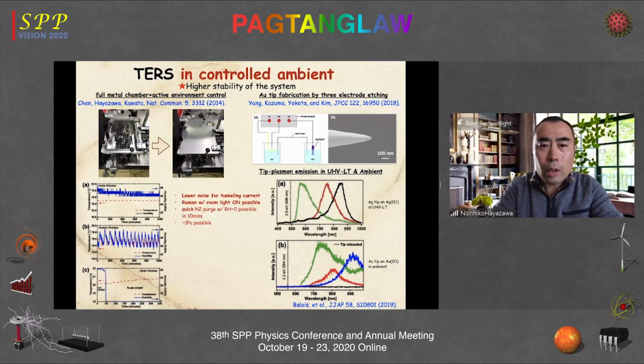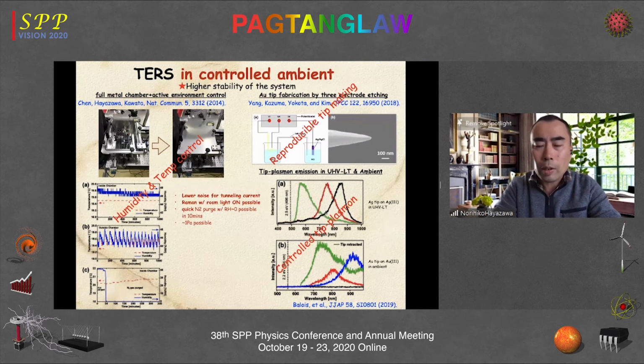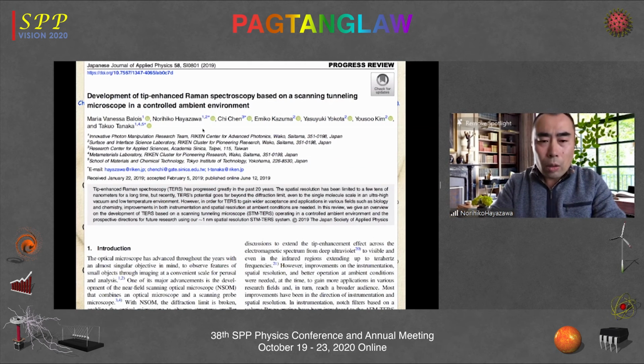After that, we have developed lots of optimizations in ambient tip-enhanced Raman spectroscopy. For example, the improvement of the humidity and temperature control using the environmental control chamber. And also we developed a reproducible tip making system using a 3 electrode etching system. And also we can now precisely tune the tip plasmon and characterize the tip plasmon by some spectroscopic techniques. So you can control very precisely the tip plasmon resonance relative to the wavelengths you are using. Recently we have compiled and summarized these efforts in a progress review published in the Japanese Journal of Applied Physics, written by Balois from RIKEN. Then after this effort, what I want to emphasize in this paper is that now we can achieve a spatial resolution of up to 1 nanometer by Raman spectroscopy in ambient environment.